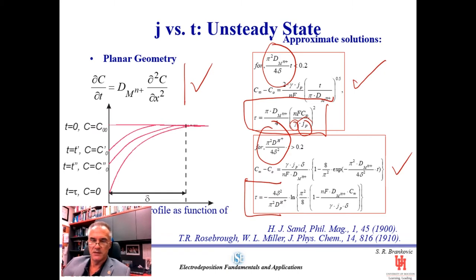Because pulsing with a certain current density longer than the transition time is not going to do any good for you. Unless you really truly want to have some powder deposit, something which is specific, you always have to design your pulse current duration to be shorter than the transition time.